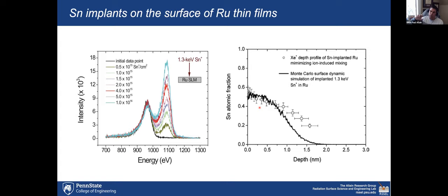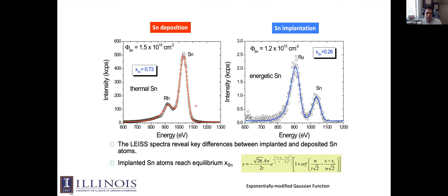And that if we decoupled the deposited thermal tin atoms and the energetic tin ions by understanding the tin implantation from ISS studies in situ, so what you're seeing here is basically tin deposited on these ruthenium and rhodium mirrors. By understanding the physics during the evolution of exposure to these tin plasmas, we were able to fine tune the energy and have the energetic tin ions, in fact, resputter material off the mirror in a way that it could be self-sustaining.